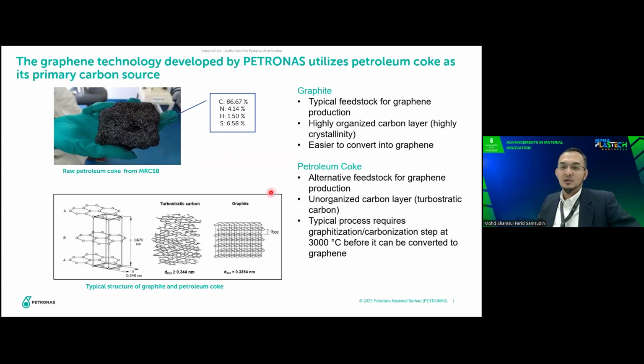If we compare in terms of technology, when we want to produce graphene, normally people will take the source of graphene from graphite. Graphite we consider as a highly organized carbon, which means it's easy to process and convert into graphene. But petroleum coke, in terms of structure, is quite amorphous. It has turbostratic carbon, so it requires heat treatment, and as I mentioned before, it requires higher temperature to improve the crystallinity of the carbon. Normally, people will use a temperature around 2,500 to 3,000 degrees Celsius.